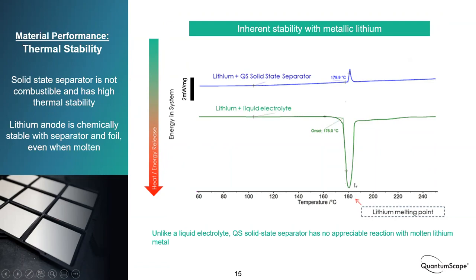And if you see a drop on this chart, that's what we call an exotherm, or the release of heat. And we can measure that very precisely. So in this case, around 170 degrees Celsius, there's a huge reaction between lithium metal and a standard liquid electrolyte. And this is one of the reasons why we've had battery fires out in the field.